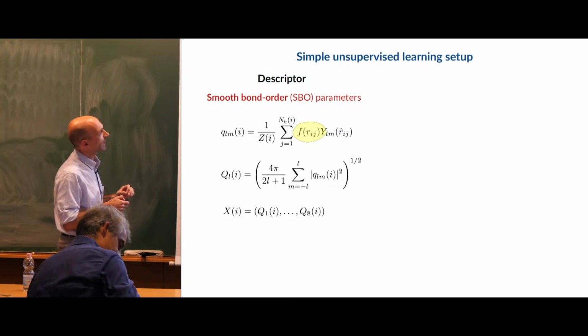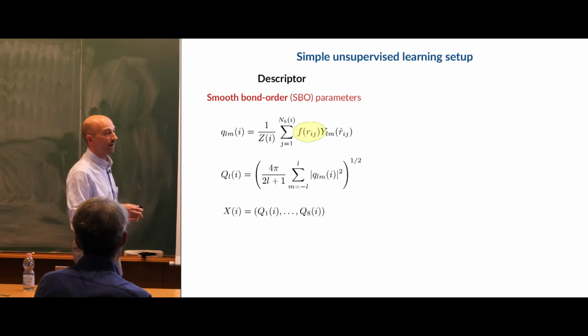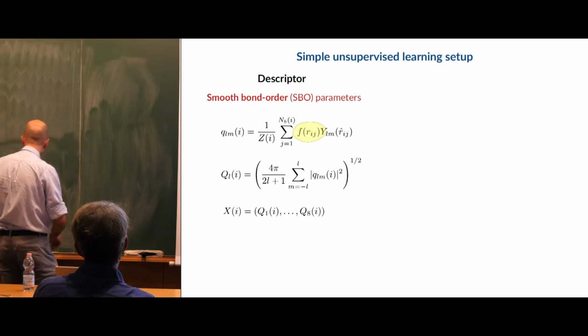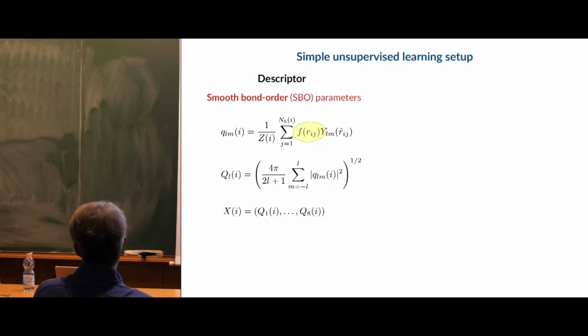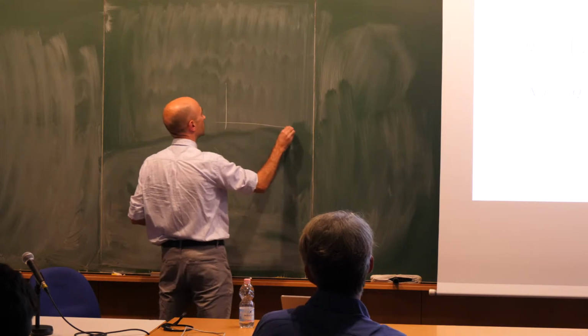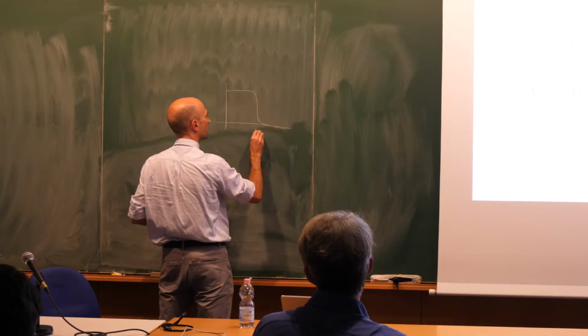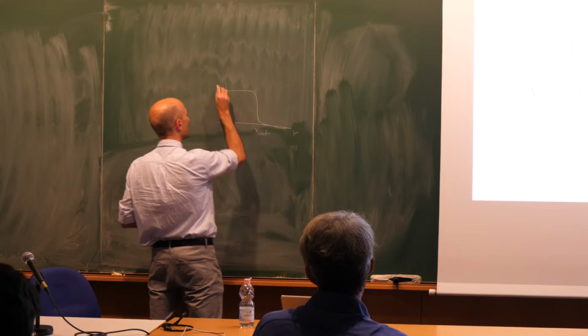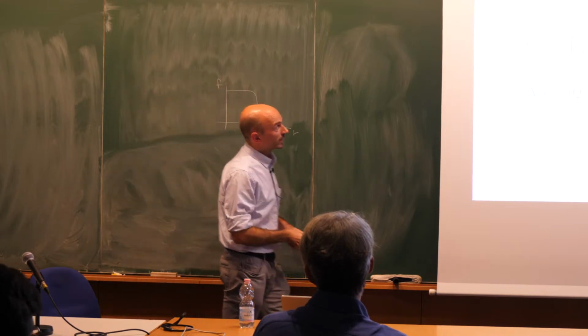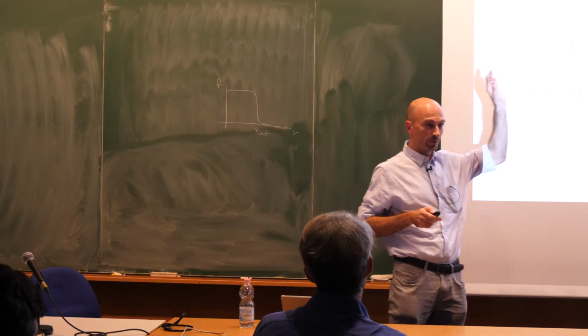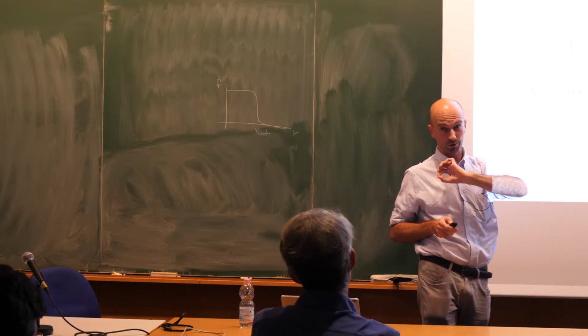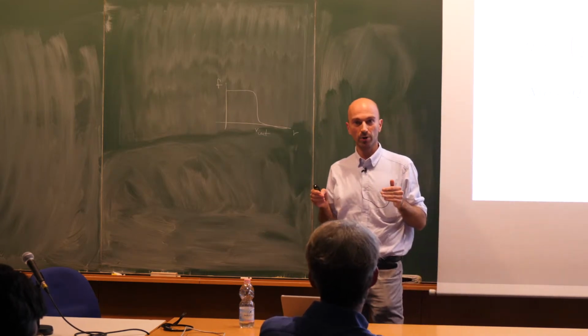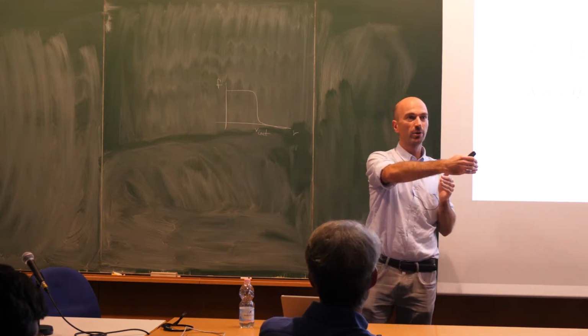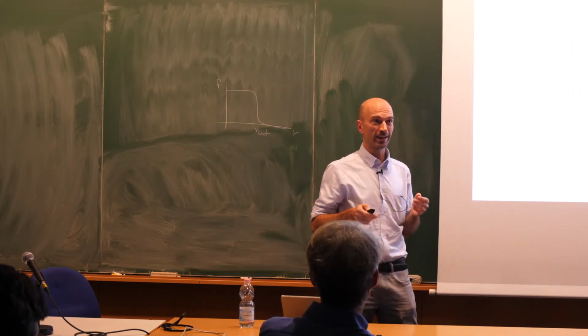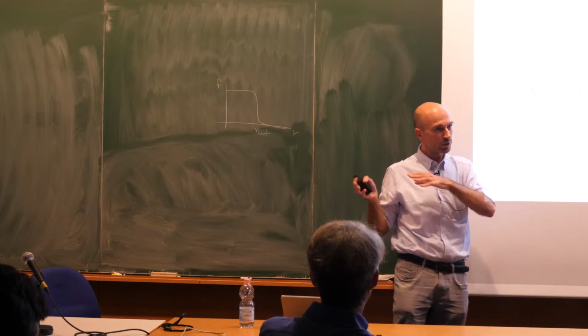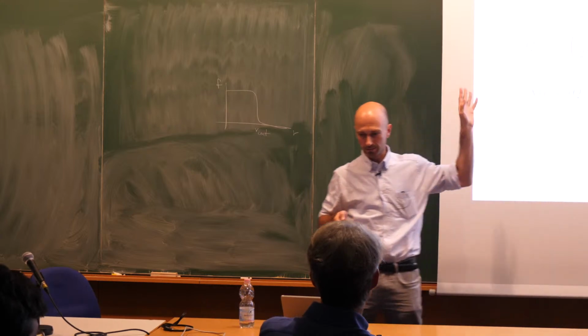Smooth means that here we add a windowing function that goes sharply but smoothly to 0 around the distance that corresponds to the first minimum of the g(r). Okay, so this is r cut, and this is our f function. This is necessary to smear the discontinuity that you will have with the bond order parameters if you have a sharp definition of neighbors. Okay, a particle leaves the first coordination shell, then the bond order parameter has a slight discontinuity. And I can show you later what happens if you don't do this smoothing.